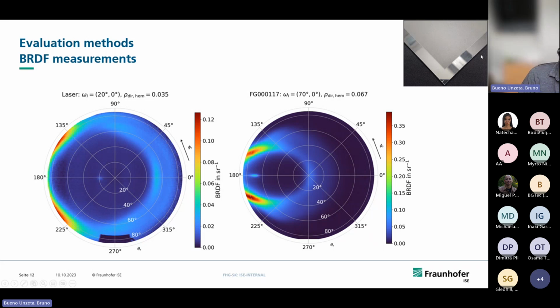So we have to move to a strongly structured glazing, like this one lasered here, to start seeing interesting things. For 20 degrees, the specular peaks have disappeared completely. The maximum value somewhere else in the hemisphere is below the threshold. For 70 degrees, we see these peaks outside the specular region, and the maximum value is 0.35, which is already the same order of magnitude as the threshold we've defined before.